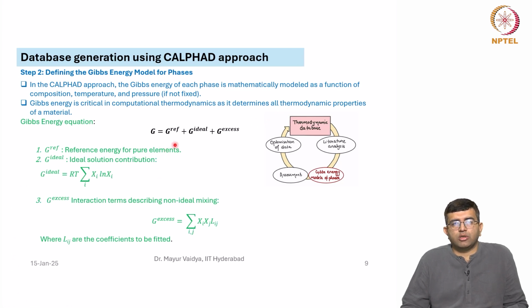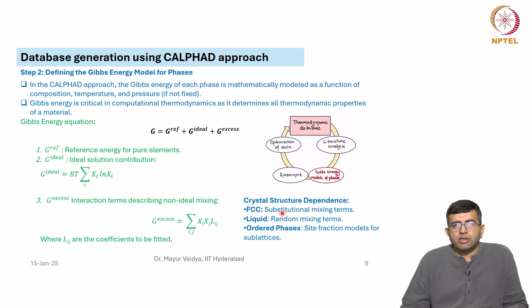Initially, when we talked about the CALPHAD approach also, G is equal to G ref plus G ideal plus G excess, and these are the excess terms that are contained, where Lij are the coefficients to be fitted. So, this excess free energy expression actually determines how much the solution deviates from the ideality, and the crystal structure dependence, the free energy is dependent on the crystal structure, FCC, liquid and ordered phases. So, for each of these different types of phases, the models that will be used are going to be different.